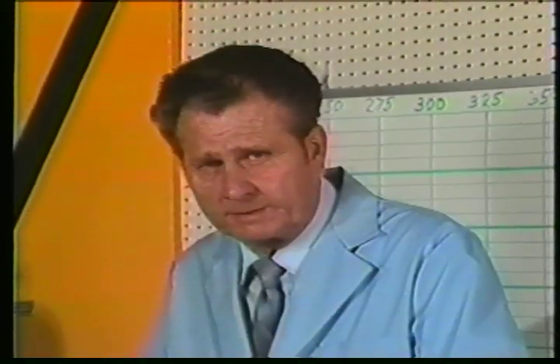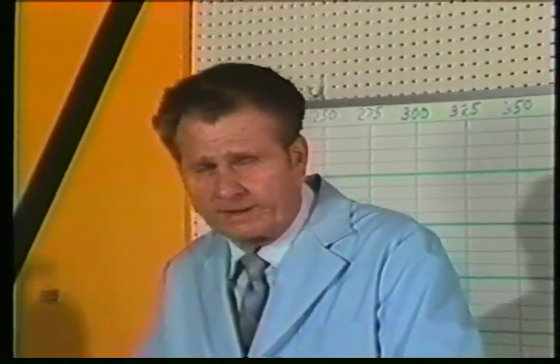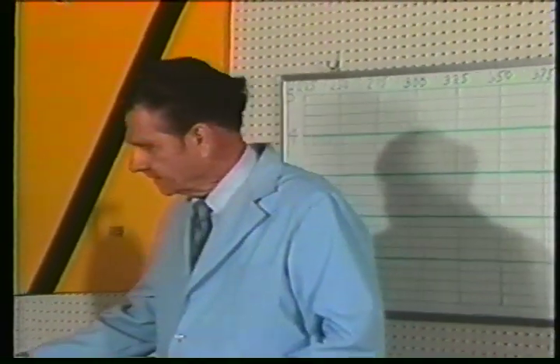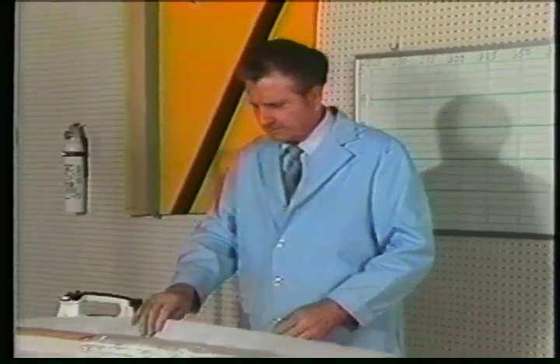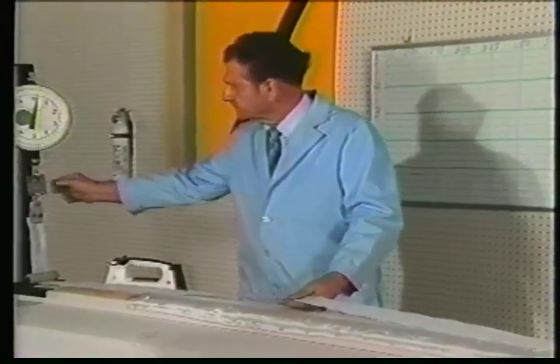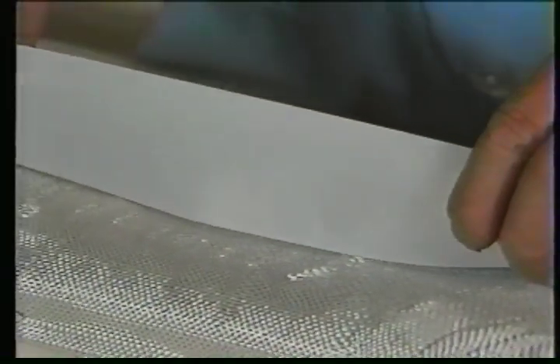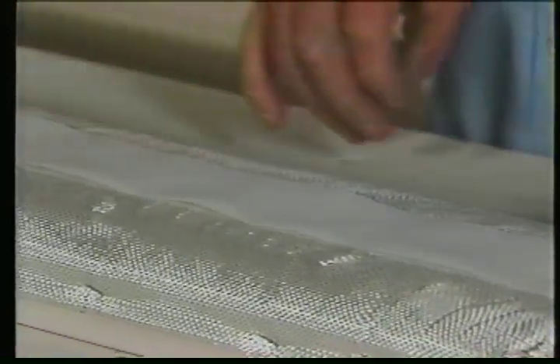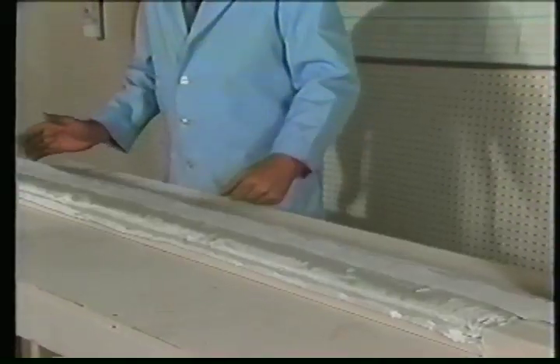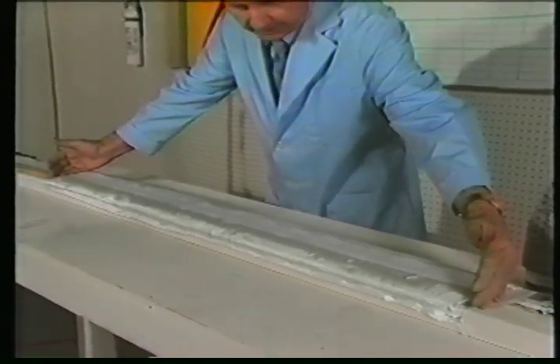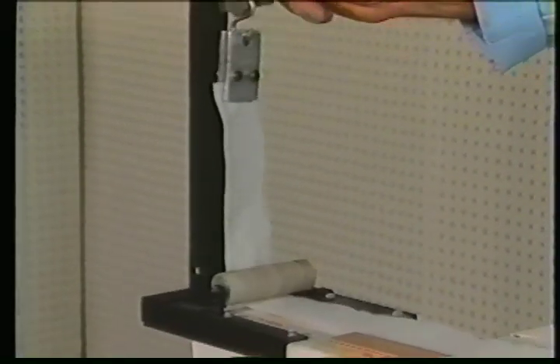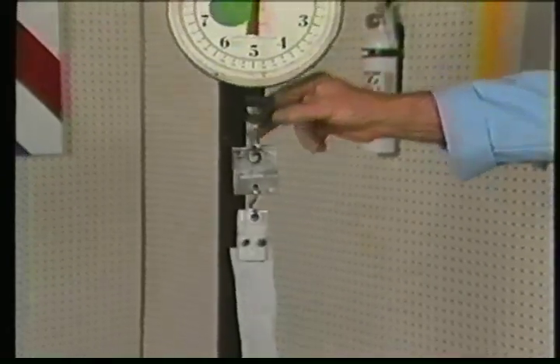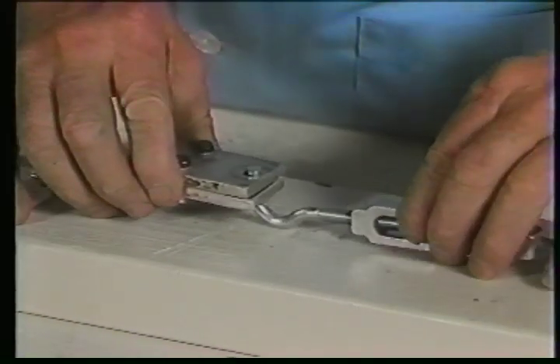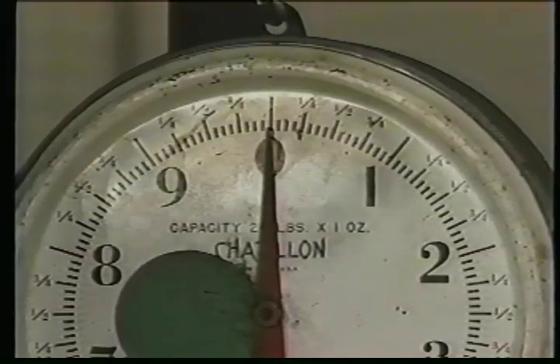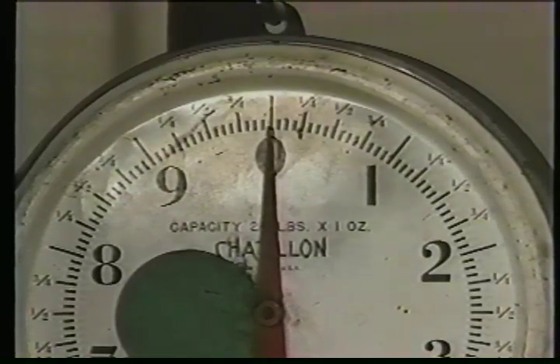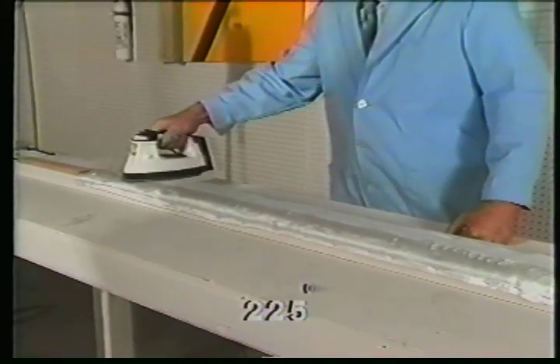To verify that statement, I'll demonstrate some of my standard evaluation tests. The first demonstration with this test rig will be fabric tension at 25-degree heat increments starting at 225 degrees. This 2-inch wide strip of fabric is styled D103, and the iron contact area is exactly 50 inches long. The tape routes under a roller to pull directly on the dial scale. All slack is removed by adjusting the turnbuckle, and the scale still indicates no tension. At 225 degrees, the tension is 15 ounces.